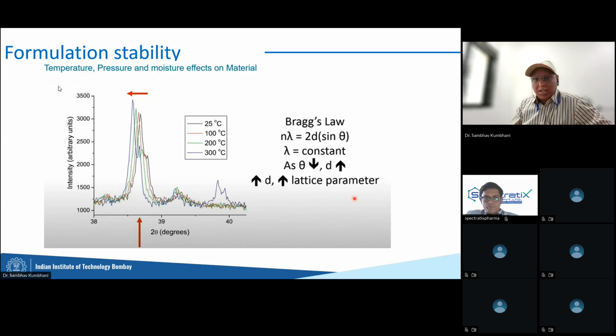Here's another cool piece of information that XRD can do. The modern XRDs allow you to make the measurement in non-ambient conditions: higher temperature, lower temperature, higher pressure, lower vacuum, high moisture content, low moisture content, things like that. You can do all that. Up to very, very high temperatures, all the way up to 2200 degrees on the positive side, and all the way down to liquid helium temperatures, 11 Kelvin, on the negative side. Same thing with pressure. You can go to really high pressures or really low vacuums. All that is possible.